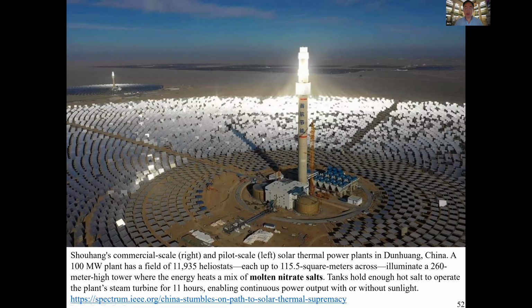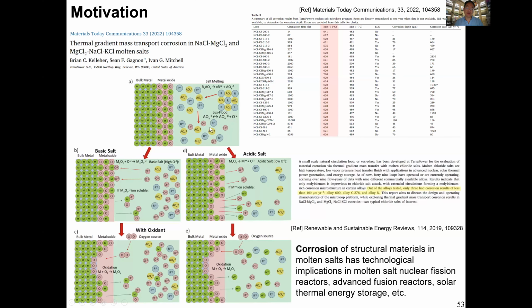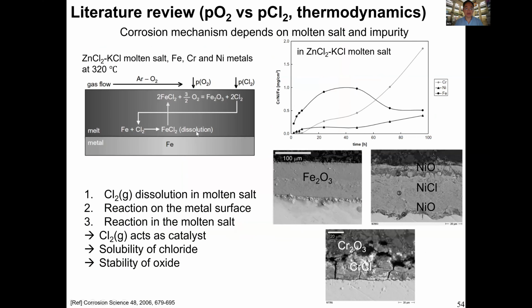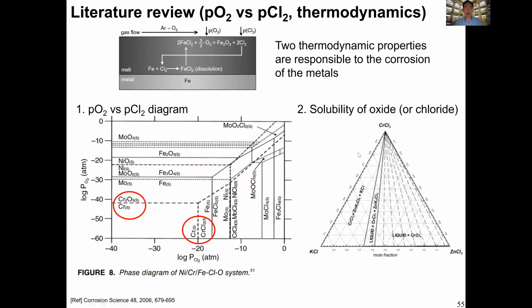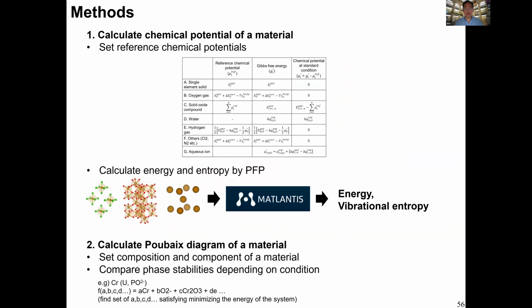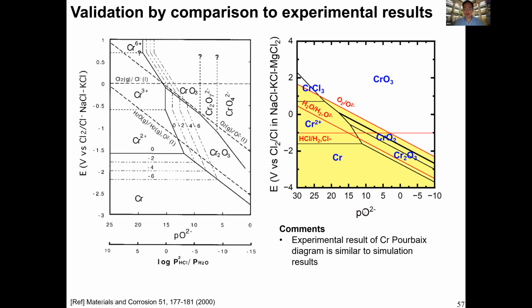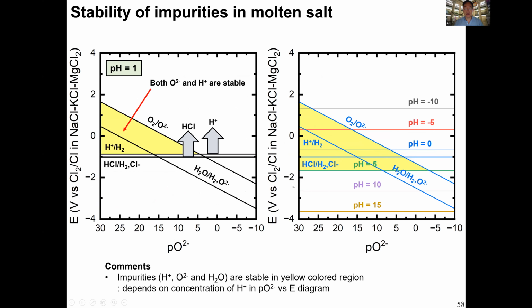So we are looking at molten salt corrosion. Molten salt is used in advanced nuclear reactors as coolant, as breeder, but it's also used in solar thermal. And to be able to go to higher temperatures like 700 Celsius, we need to look at compatibility of structural materials with different molten salts. We form all kinds of phases in the oxide scale. And the key point in this is how the molten salt cares about the moisture, for example. So we need to do Pourbaix diagram calculations, and we are now doing quite high-temperature calculations and trying to get access to these kinds of Pourbaix diagrams. And this is ongoing with Hanyang University, in a collaboration.